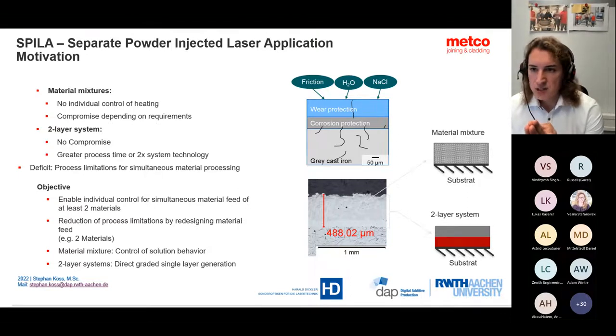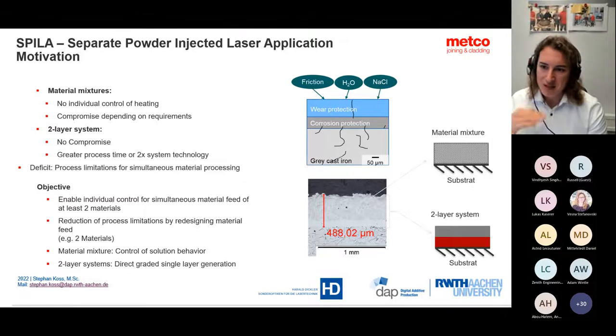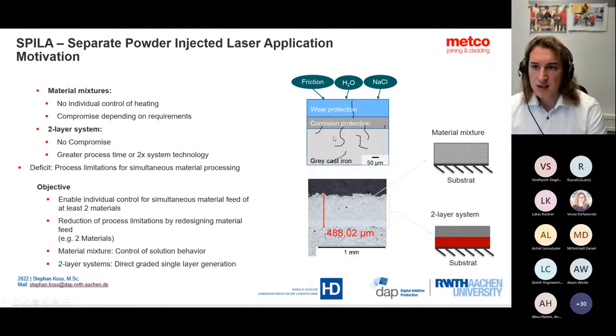So typically nowadays, how people work, they use some type of buffer layer, which can provide corrosion resistance, is ductile, and might be much easier to deposit on cast iron, as an example. And then you put a second layer, which might have some carbides in it and give you also wear protection. It's a well working process. However, there was a huge disadvantage in terms of economics because you need to put down two layers, which takes more time, more material consumption, and might cause troubles on the customer side as they simply do not want to pay for it.